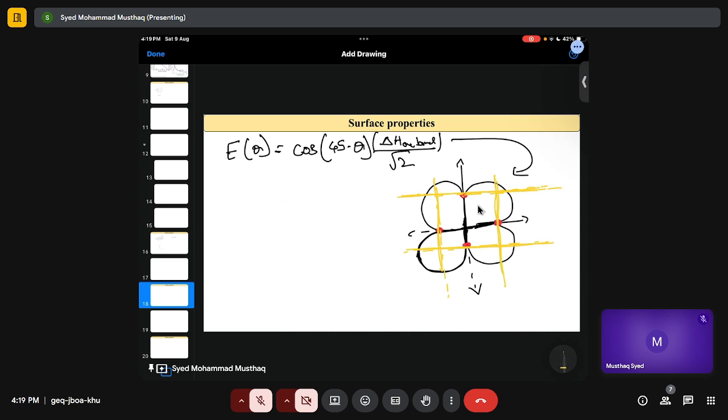And these curves are at minimum energy. Whenever you draw a tangent at that point, they will cut the surface like this. And this collection of tangents will tell you the equilibrium shape of any object.